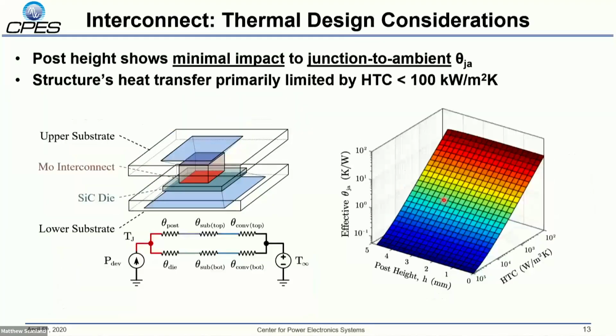And so if we change this picture around a little bit and instead look at the junction to ambient thermal resistance, now this plot becomes a 3D plot where we're looking at the post height on the x-axis and the heat transfer coefficient on the y-axis. We see that the effective junction to ambient thermal resistance is actually a strong function of HTC, and not as strong a function of the post height.